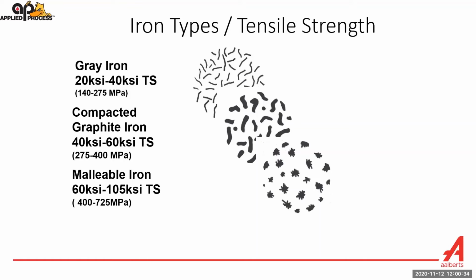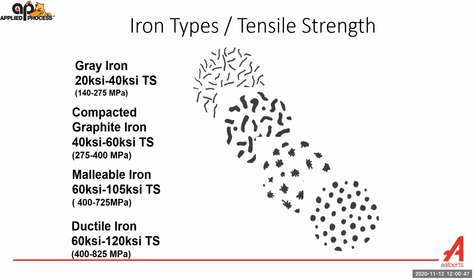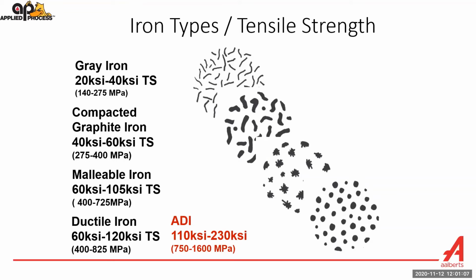Years ago, they used to make what's called malleable iron. It requires a heat treatment to get the graphite into this shape. But again, as the graphite shape turns from flake to more round, the mechanical properties continue to increase. And then in 1942, somewhat by accident, ductile iron was invented through the use of a magnesium addition. And ductile iron can have strength of 60 KSI to 120 KSI, which is strong, but still not as strong as some of the steels that are out there. But if you austemper it, you can dramatically improve the mechanical properties further, essentially doubling or tripling the strength of the material. Again, you increase the strength. Now you can decrease the weight of the component if the load carrying capacity is increased.